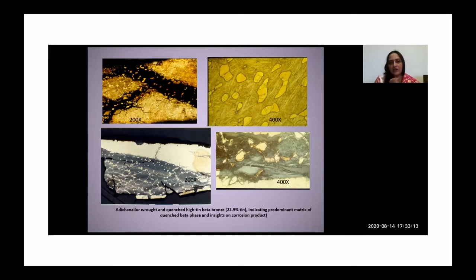But look at the dark patches running in there. That's not just void; it is related to something. And you see there are still some islands of the alpha solid solution phase within that. When you look at those dark areas under polarized light at higher magnification, you can see that the beta phase has been preferentially attacked. There is some preferential corrosion here, maybe because the beta phase is what we call a metastable phase. Because it's metastable, unless you quench it at high temperatures, it doesn't form at room temperature. And being metastable, it tends to get attacked more easily. So the needle-like beta matrix has been eaten out in those corroded areas.